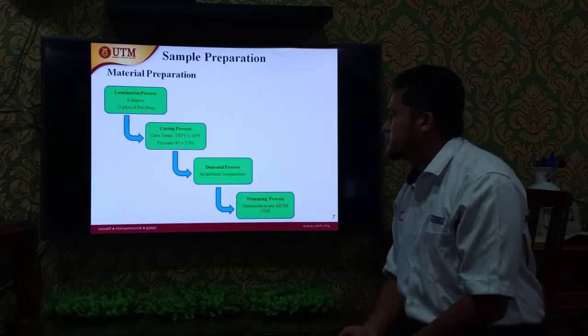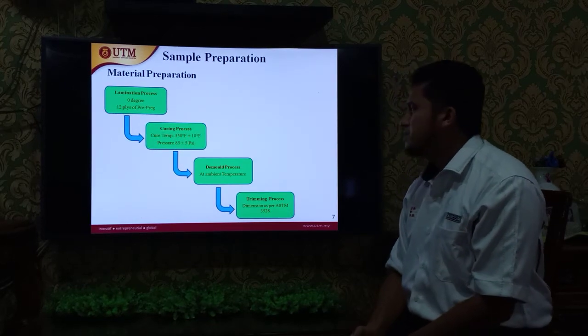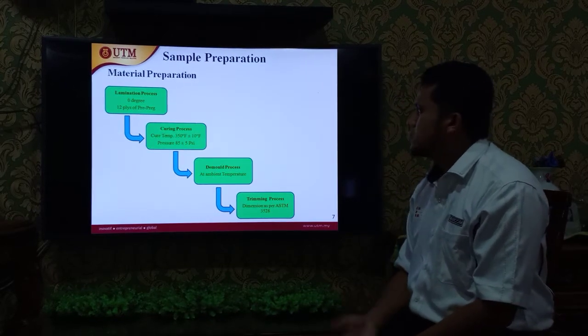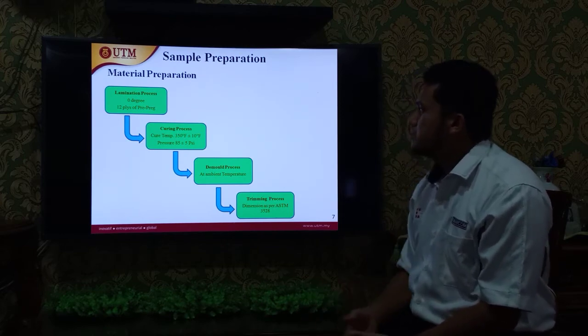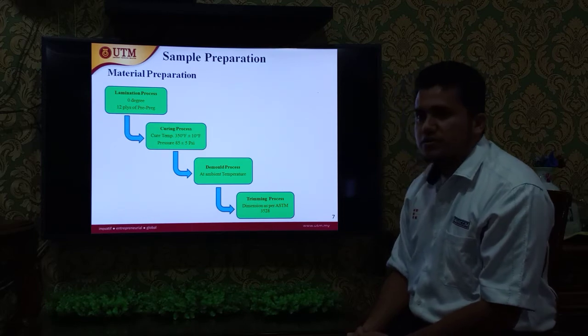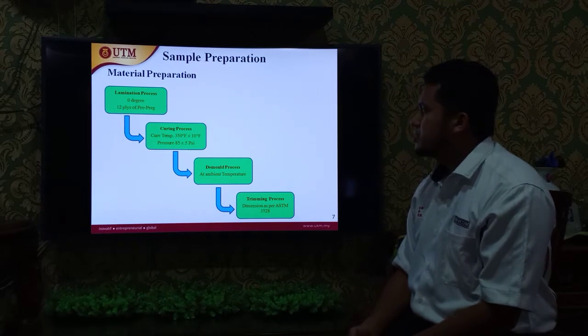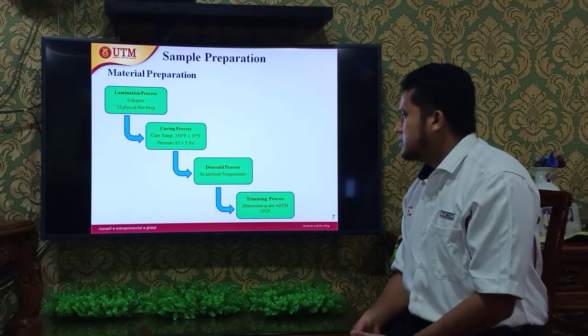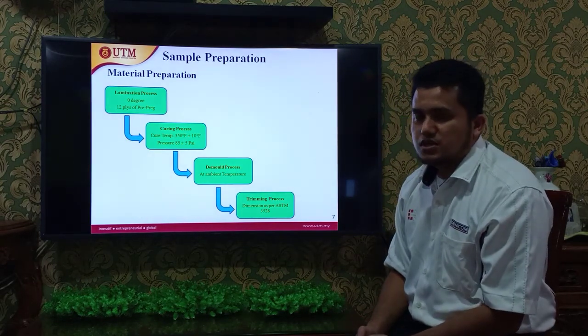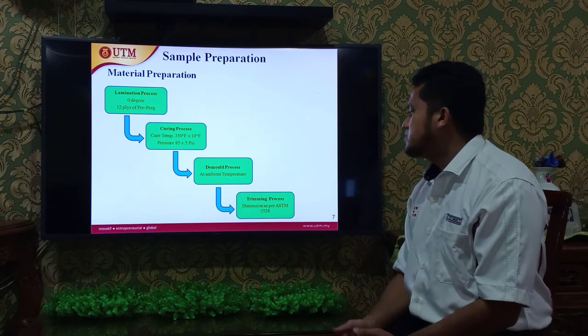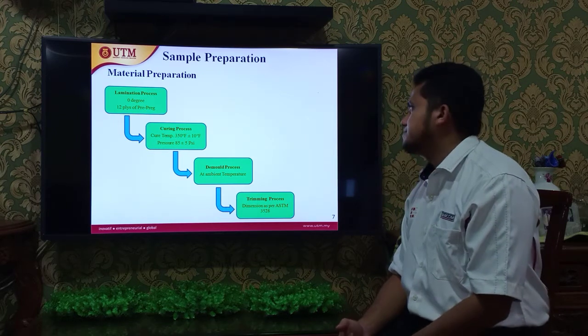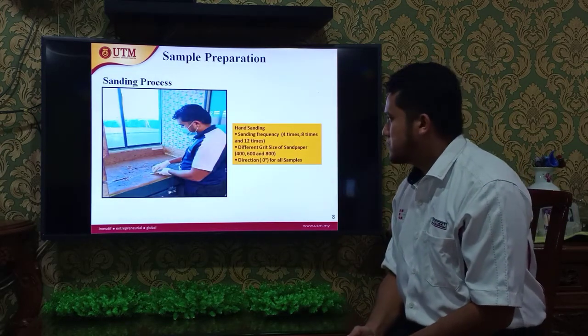This is the sample preparation. For materials preparation, the fiberglass lamination process is 0 degree, 12 ply of prepreg. After that, the curing process: cure temperature 350 Fahrenheit, plus minus 10 Fahrenheit, pressure 85 plus minus 5 psi. After that, the demold process at ambient temperature, which is room temperature, and lastly the trimming process as per dimension at ASTM 3528.